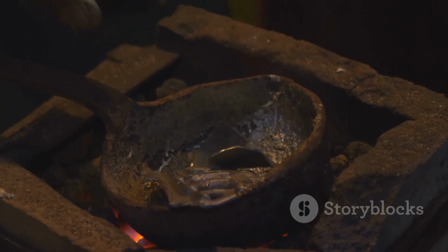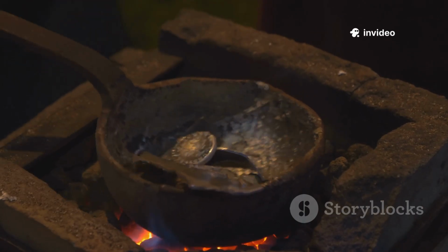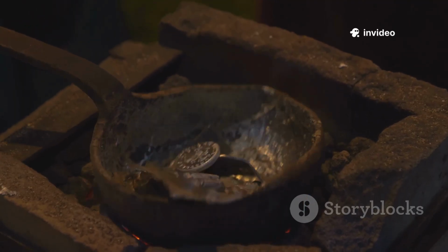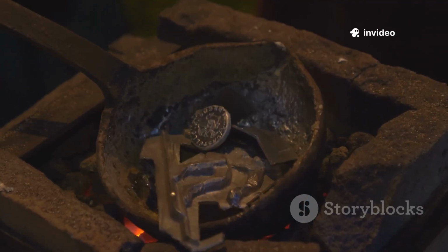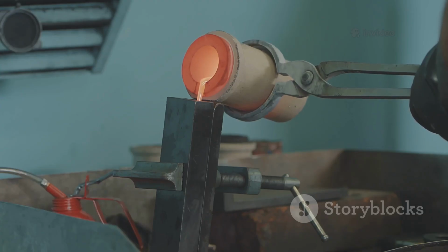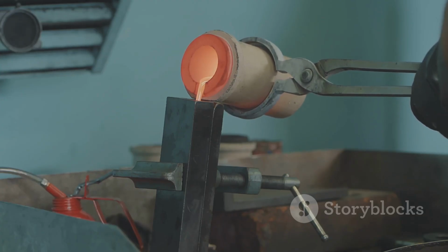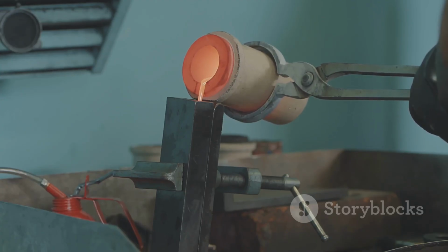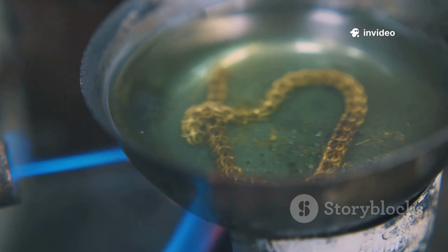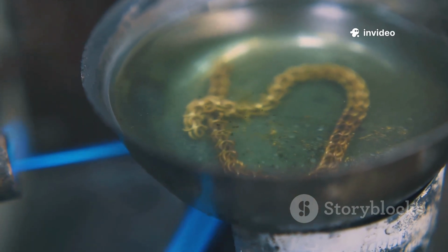The most common and effective refining method used today is the Miller process. The doré bars are remelted in a large crucible inside a furnace. A long clay pipe is then inserted into the molten metal, and a stream of pure chlorine gas is bubbled through it. The chlorine reacts with almost all the other metals like silver and copper, but not with the gold.